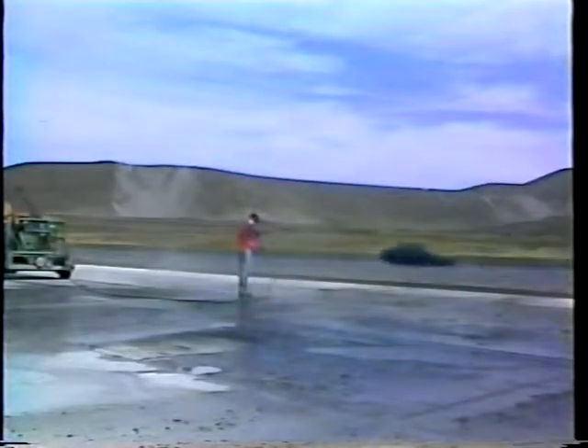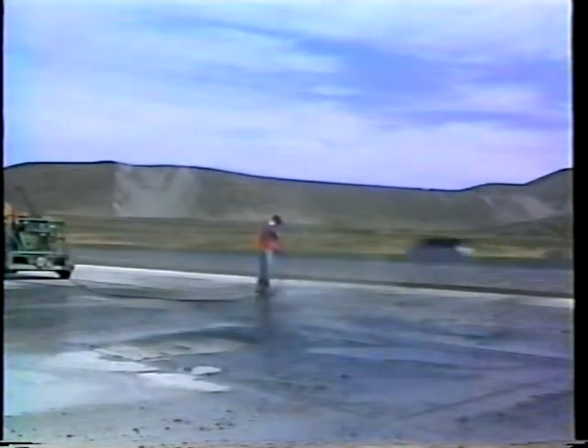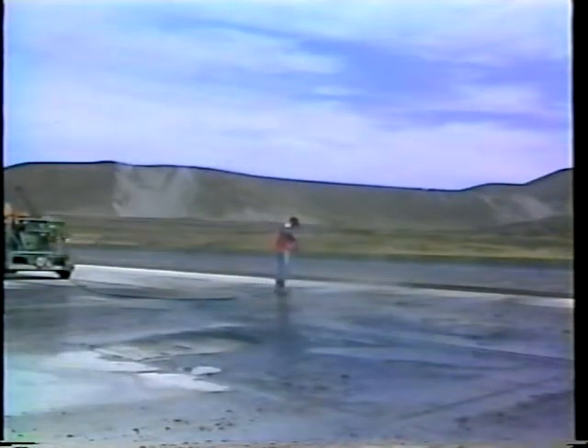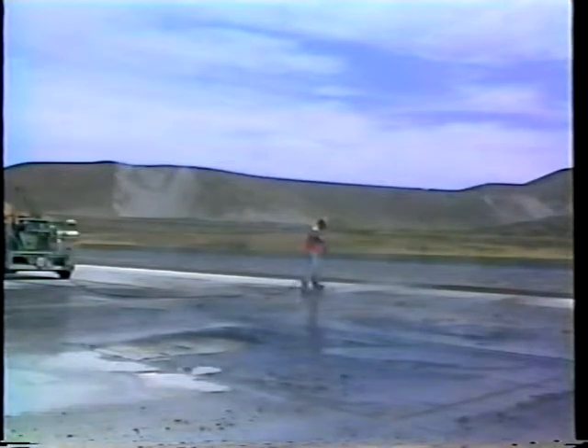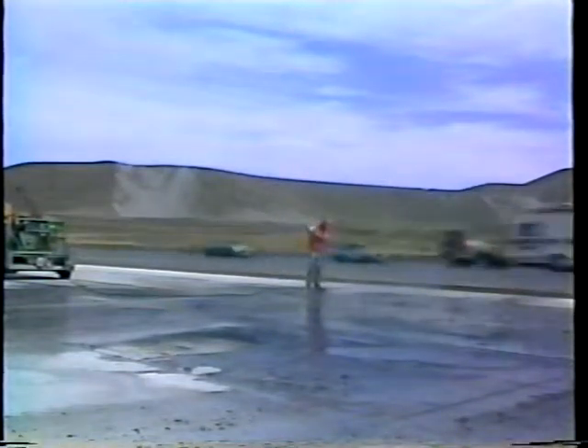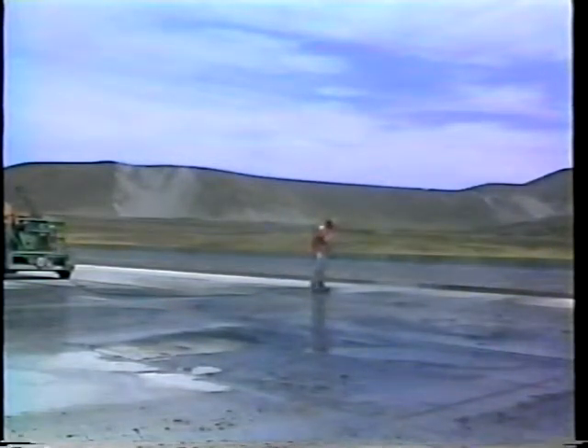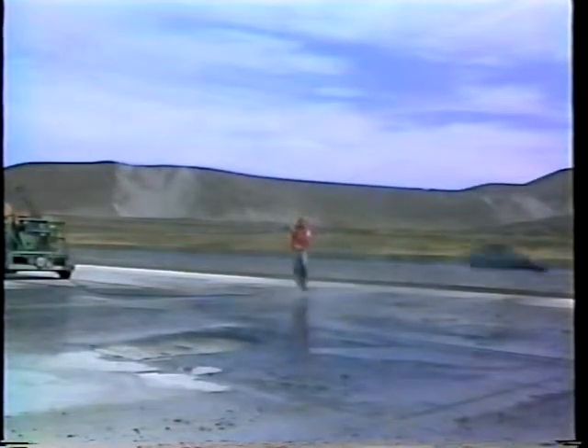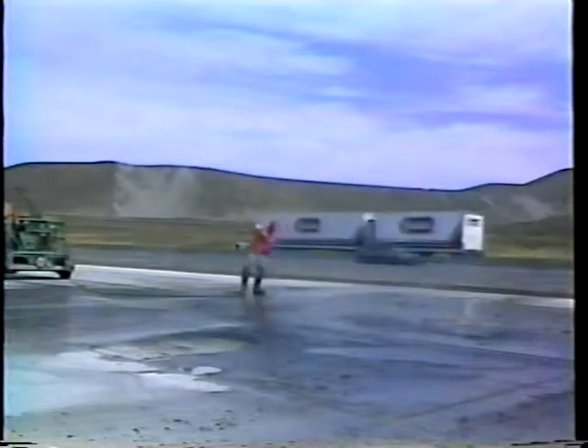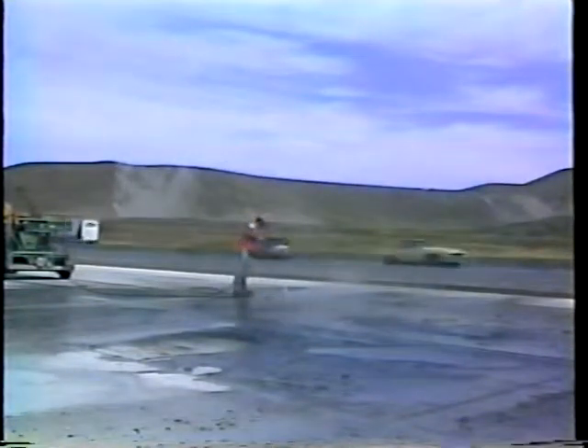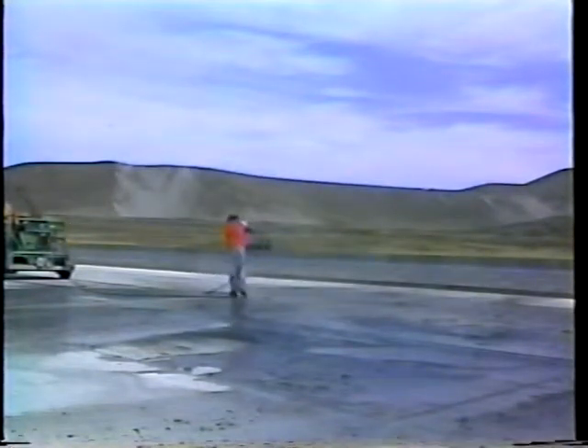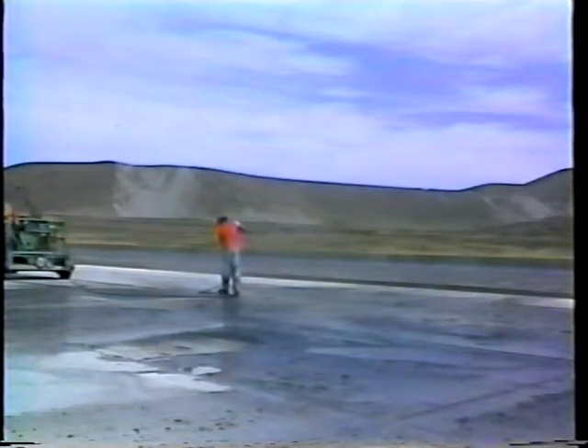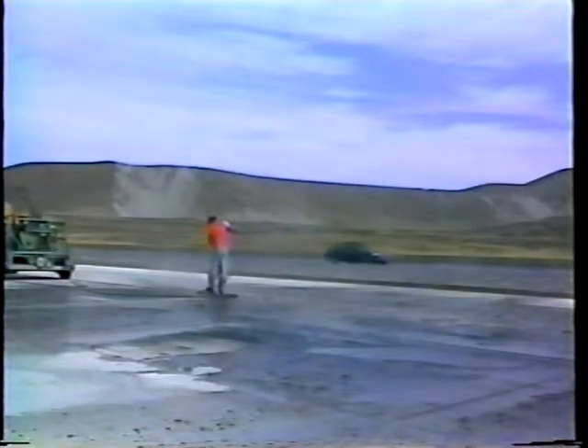The third option is water blasting. Here, water pressures of up to 30,000 psi are used to remove the deteriorated concrete. This method has two advantages. First, all the material can be removed without the danger of damaging the surrounding concrete. And second, water blasting leaves a clean-cut surface with excellent roughness and angularity, which will promote bonding with the repair material.